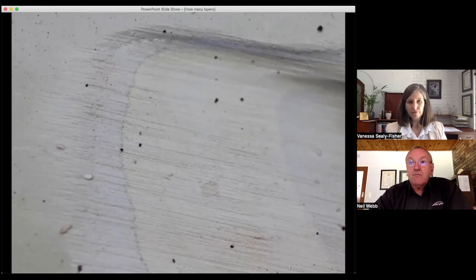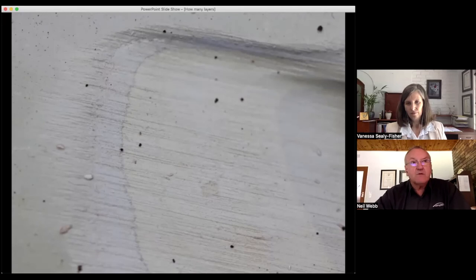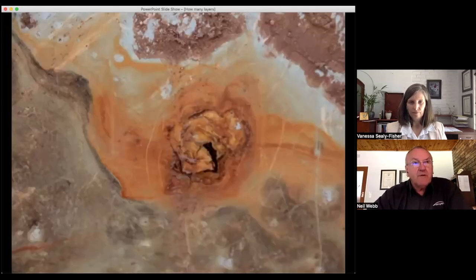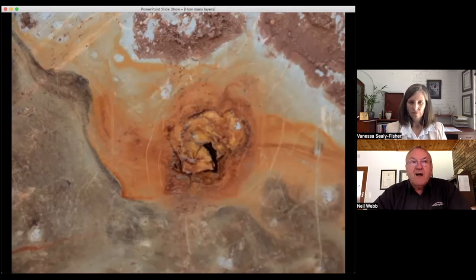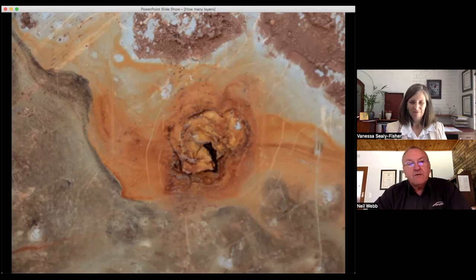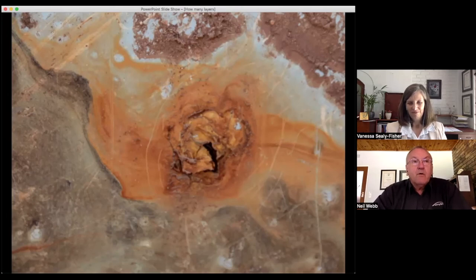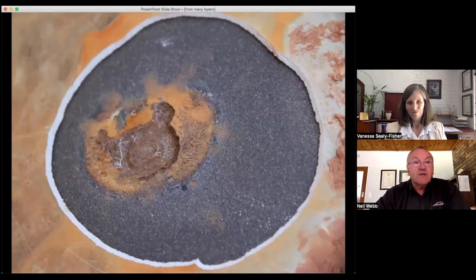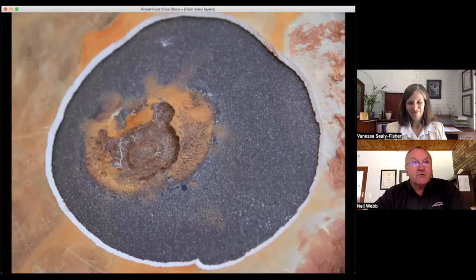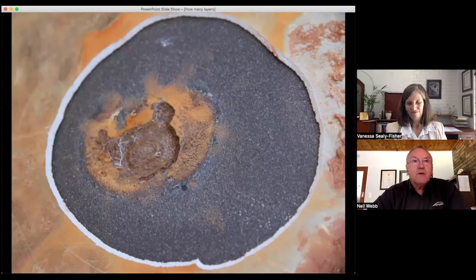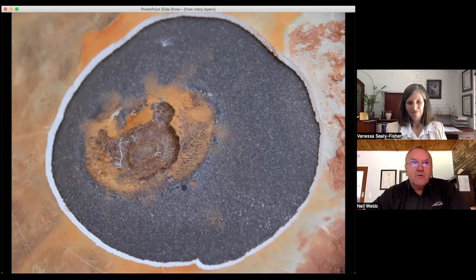We've got some really good case histories of polyurethanes in the field, as with other high-performance coatings—I'm talking specifically about their electrical resistance characteristics. The challenge is that if there's damage to the coating, because of the high electrical resistance, any stray current interference, AC or DC, is concentrated into very small areas. A fairly innocuous-looking chip can result in significant metal loss if you don't have temporary protection during construction.